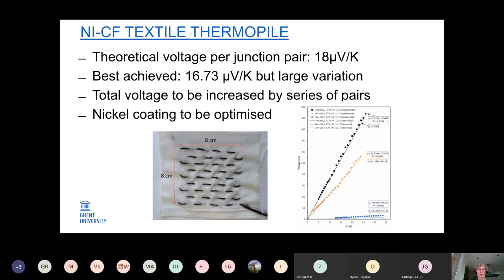And the total voltage can be increased by having multiple pairs in series, which is a linear effect actually. The nickel coating has to be optimized because, of course, if the coating is not properly done, the outcome will be lower, and in some cases it can be as low as 3 microvolts. So it's really important to work on this in order to have a good result.